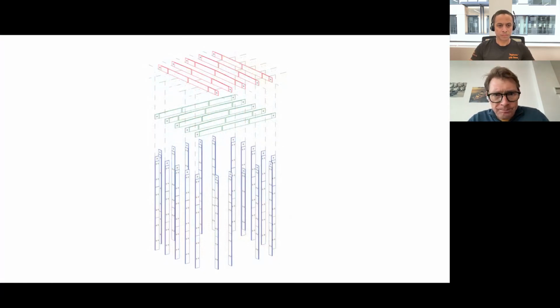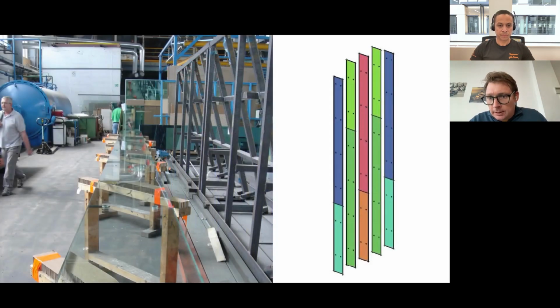So this is the internal frame, and you can see that the roof panels are split and they're joined with steel fittings. But the columns are manufactured from just over 6 meter tall panels, but they're cross laminated. And if we look at this next slide here, on the diagram on the right, you can see how those panels are overlapped, similar to the way in which you might cross-laminate timber. And our approach was that we thought the interlayer would be stiff enough to provide the shear resistance between those panels. But as this was our first consideration, we also bolted through the glass panels to provide that shear capacity.